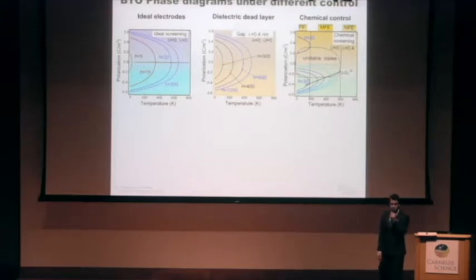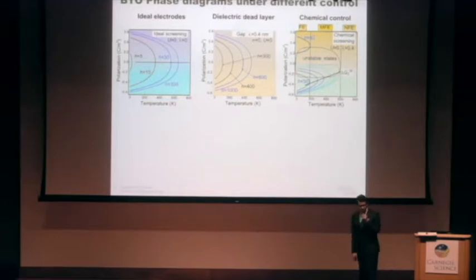You can also introduce a dielectric dead layer. This is basically just a finite thickness over which the potential will drop to the external applied potential. It doesn't change the calculations at all. Basically, you have a slightly reduced polarization, but there's nothing qualitatively different about these two cases. But now let's look at the more interesting case where we have this electrochemical boundary condition.